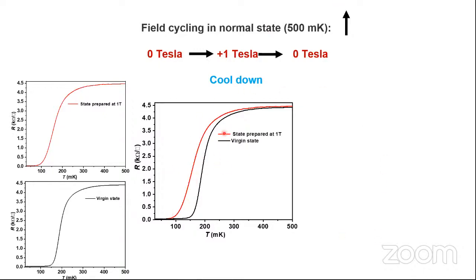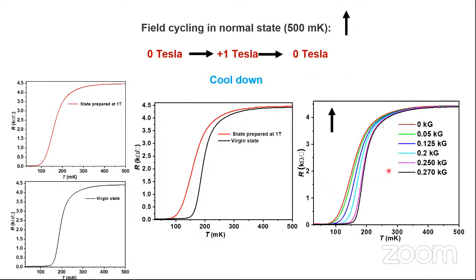That means the property is of the interface itself. There is no extrinsic origin of that. Now, this is the RT after doing the field treatment. Then we started applying a magnetic field in the same direction in which the field cycling was done, that is upward. This arrow indicates the direction in which the field is applied. And we see that with increasing magnetic field, the critical temperature goes up, and at 0.27 kilogauss, we recovered the pristine state RT back.